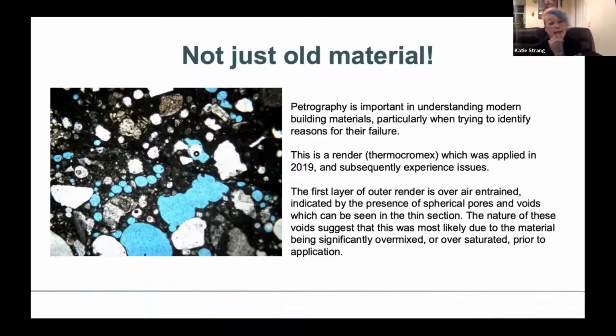In this particular sample though, it's just quite interesting. This was only applied in 2019, so this is last year, and pretty much straight away it started to experience issues. And these perfectly circular voids in here show that the render has been over air-entrained, and it suggests that it was likely because the material was significantly over mixed. So they basically mixed it too much and there's too much air in your mortar, or it's been oversaturated with mortar.